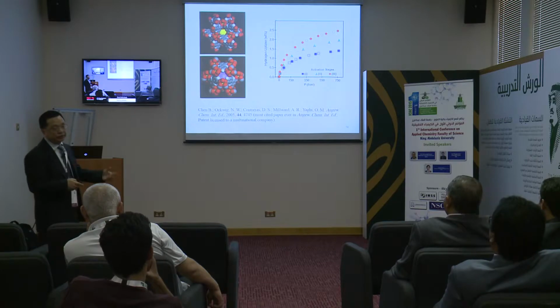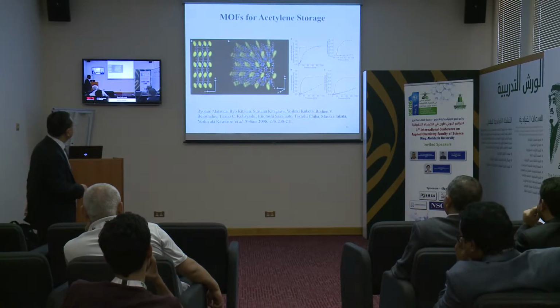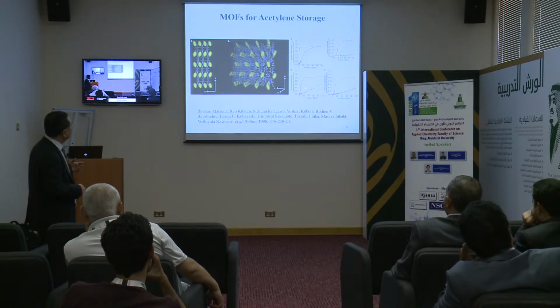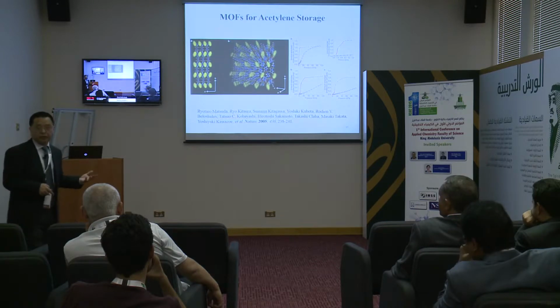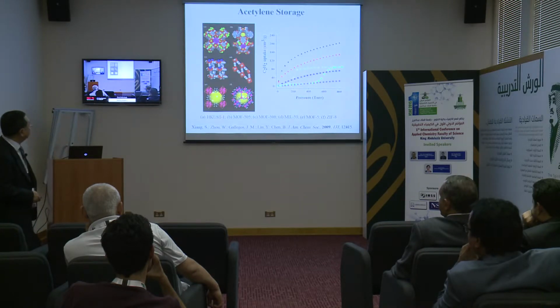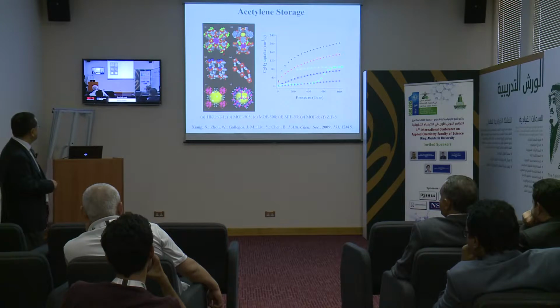So this conceptually is important. And for acetylene storage, initially we realized by Susumu Kitagawa, but this material has a small pore, so its uptake is quite low. So we realized that we should use a different kind of porous metal-organic framework.